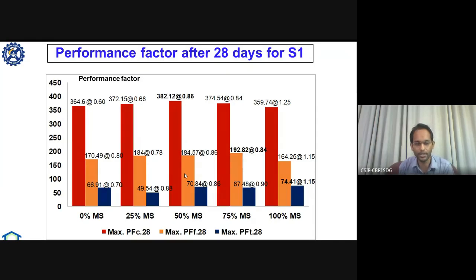So what we have found is that slurry modifies the microstructure and packing density of the composites. Therefore, the overall performance factor was higher for 50% replacement of fine aggregate. Normally in Indian code IS 2185 part 4, the value of performance factor for strength is given, not for flexural and tensile, but I have mentioned them here. The performance factor for compressive strength given is 350. So you can see here at 50% replacement level, our value was 382, which is quite more than that.